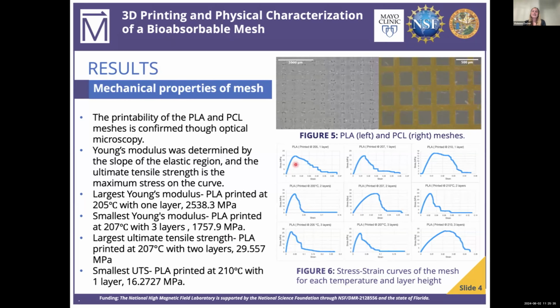So then we use the elastic region here to determine the Young's modulus with the slope. And then the ultimate tensile strength was the highest point on the graph. So we found here the largest Young's modulus was PLA printed at 205 degrees Celsius with 1 layer. And this was 2,538.3 megapascals. And then the largest ultimate tensile strength was PLA printed at 207 degrees Celsius with 2 layers. And this was 29.5 megapascals.